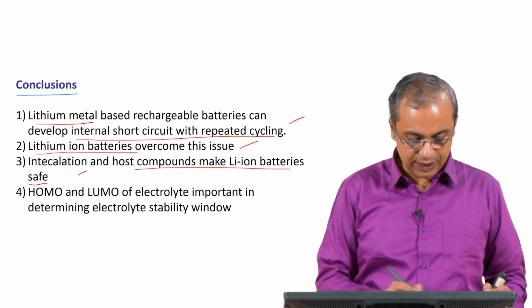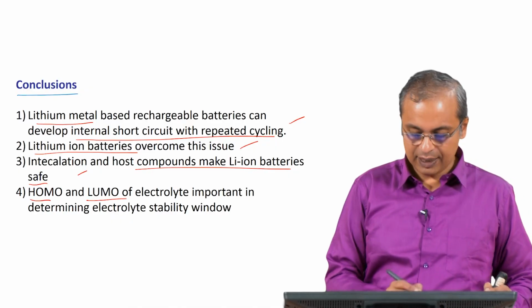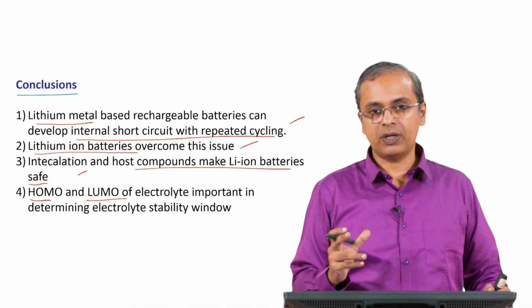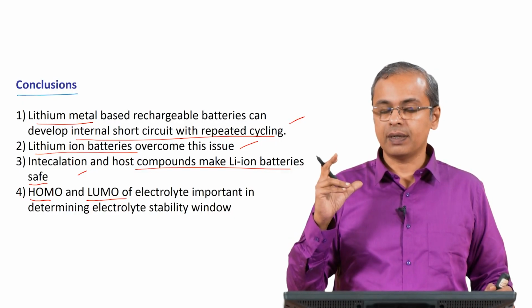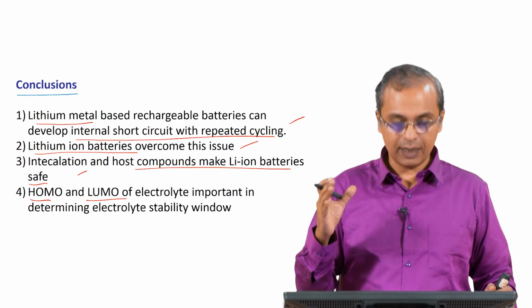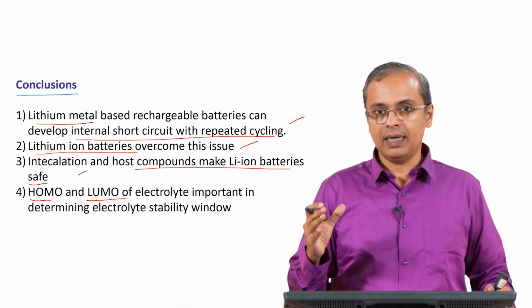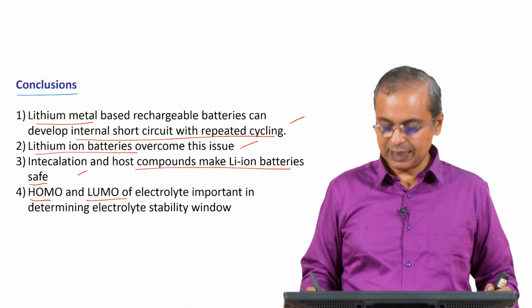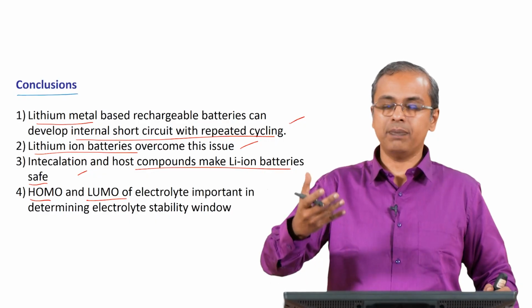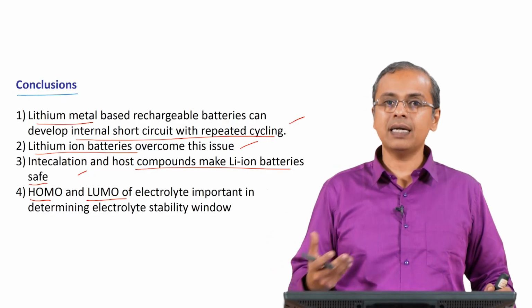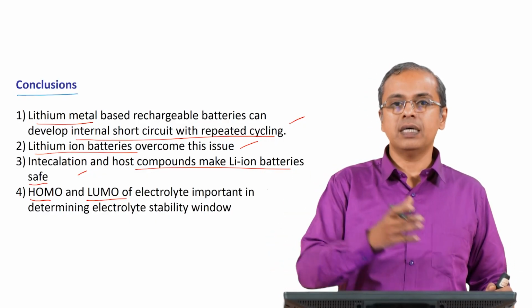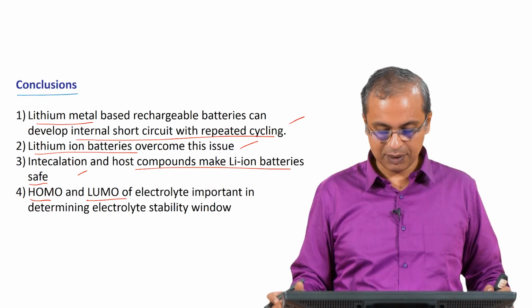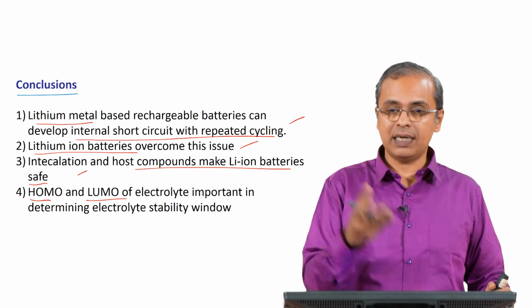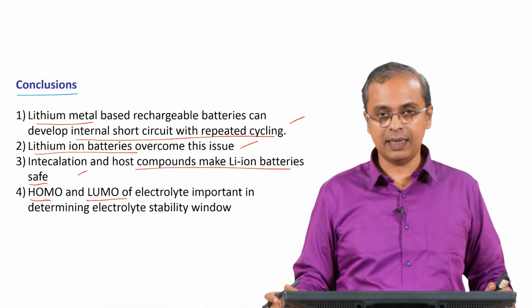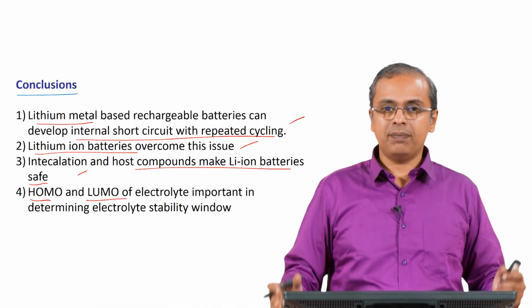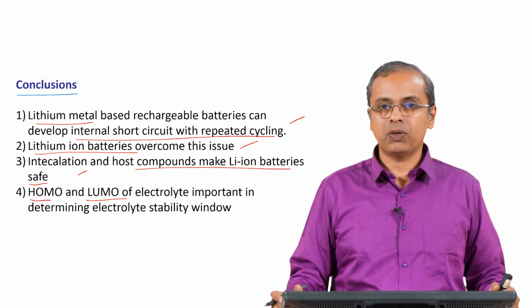and we also saw that it is very important to match the allowed operating window of the electrolyte with the energy values associated with the anode and cathode of the battery. Only when you do that, the system is actually safe, and only then you will actually get current meaningfully out of the battery, otherwise you will have the electrodes reacting with the electrolyte, which is a completely undesirable situation, and you are actually wasting the electrode, you are also wasting the electrolyte, you will not get any current in the external circuit. So, that is our main conclusions for this class on lithium ion batteries,